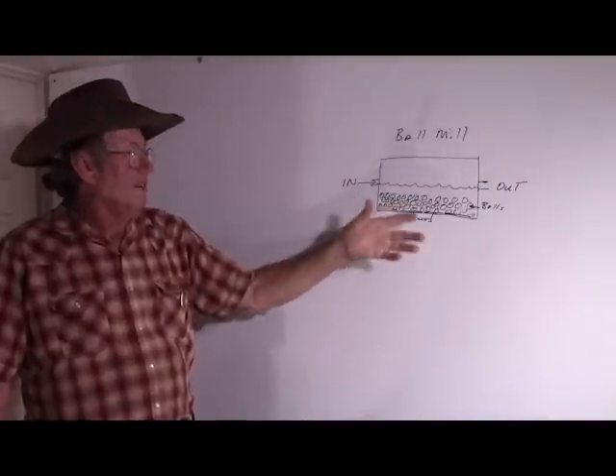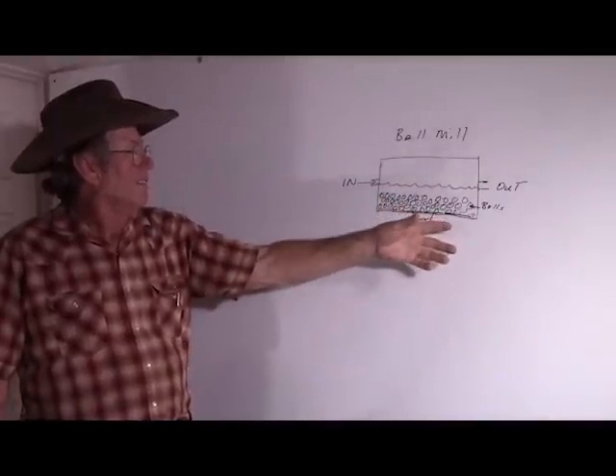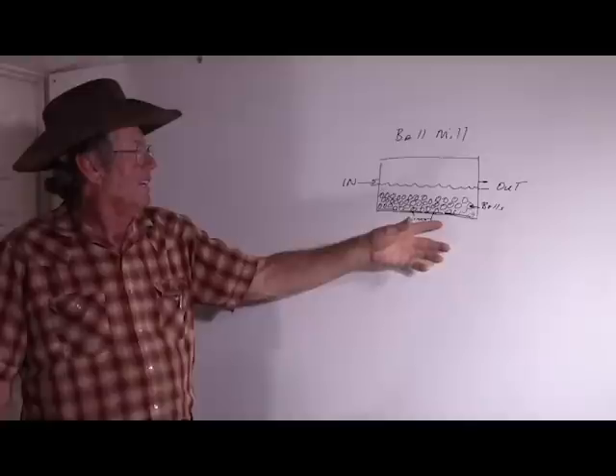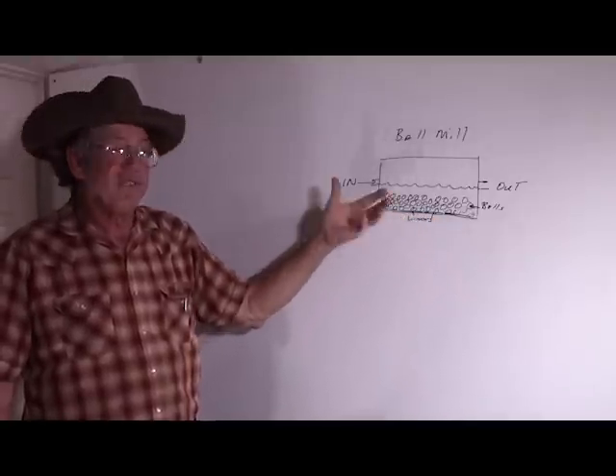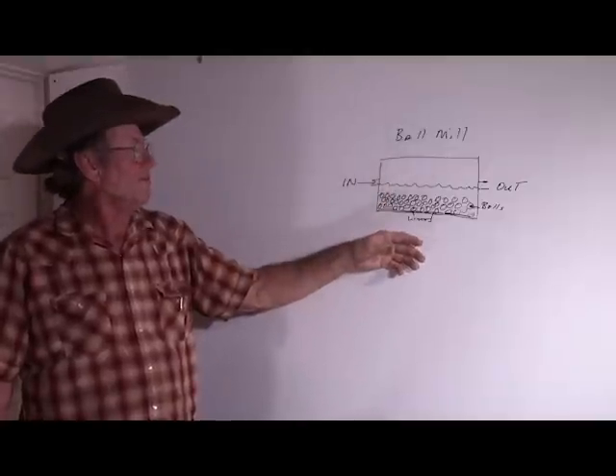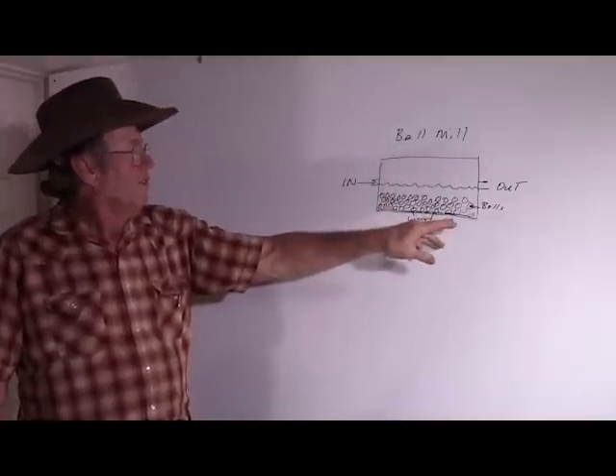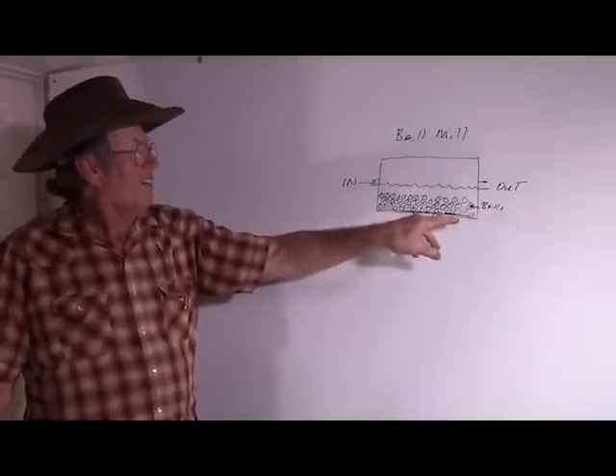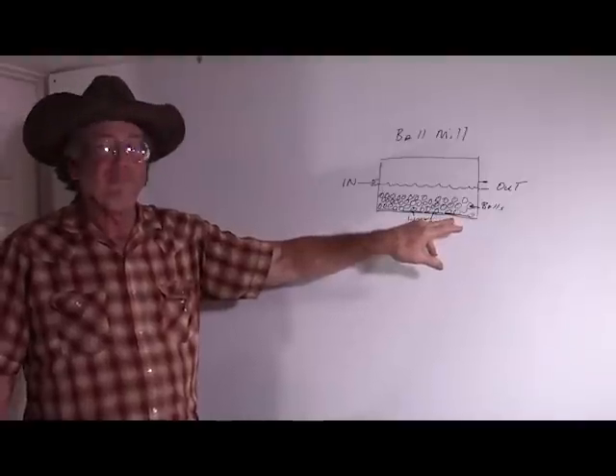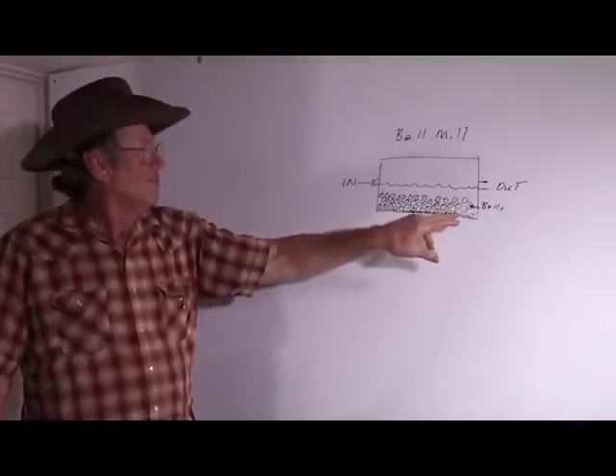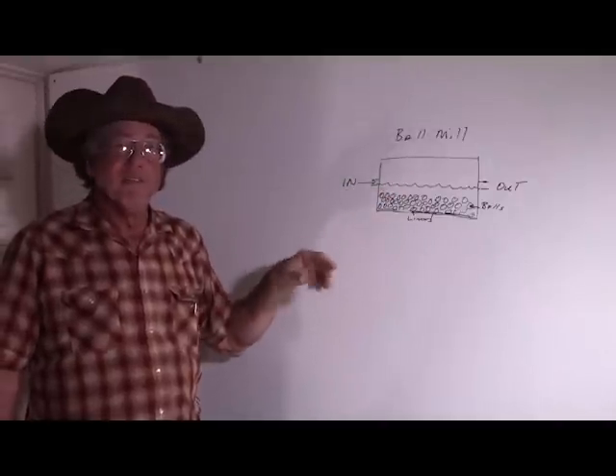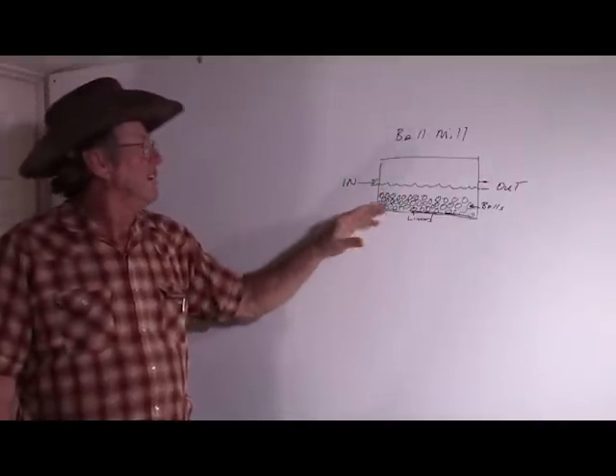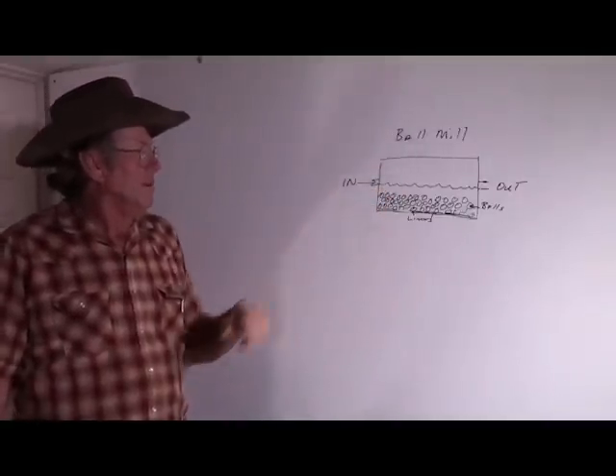Now, in order to keep a ball mill from wearing out over time, they're typically, at least in the commercial versions, covered with liner plates inside which are removable and replaceable. That gold will often get behind those liner plates and be essentially lost forever. If you have coarse enough gold, the amount that can wind up in one of these ball mills is very large, and it's not something you're going to be able to get out again.